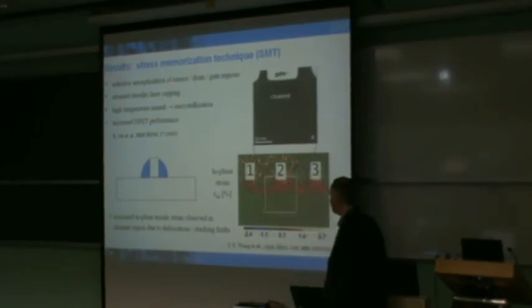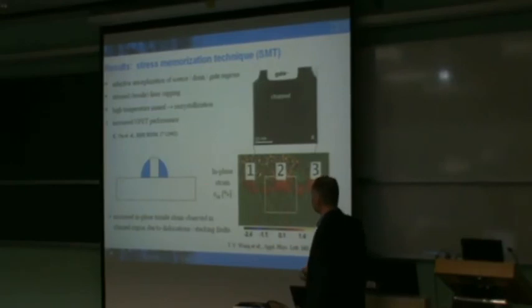Okay, I think I'll go quickly to the end story of one technique that we use to help utilize dark field holography. And one of the aspects was an understanding of a process called stress memorization technique, in which actually by amorphizing the gate region as well as the source and drain region, and then by capping the structure and then recrystallizing, we're actually changing the strain state. And you can induce significant in-plane tensile strain here.